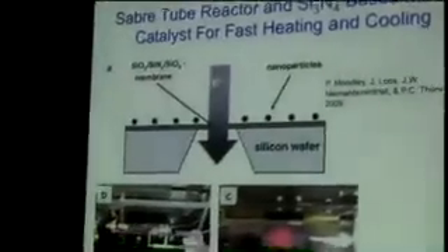I want to show you our reactor system. So for these model catalysts, we use a thin film of silicon nitride, which is in an EM grid. That grid is placed in this reactor. This is the sabre tube. It is heated resistively, so we get heating rates of 100 C per second. You can heat up very quickly, you can cool it down very quickly. Alright? So let's see what happens on model catalysts.